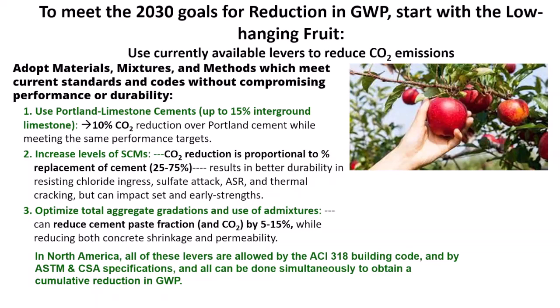You can increase the level of SCMs. Fly ashes and slags have been used for years, but typically at lower replacement levels. A lot of DOTs limit the maximum SCM level to amounts that don't allow you to optimize and reduce further, but you're getting a direct reduction in proportion to what you're replacing of the clinker. And optimizing aggregation, as I mentioned, if you just have a fine aggregate and a coarse aggregate, you're not optimizing your gradation. Most ready-mix plants or batch plants in North America use a fine aggregate and a coarse aggregate. The pavers often have an intermediate aggregate, which allows them to reduce their paste content, which is required for pavements. They don't get cracking and volume change, or reduces it.